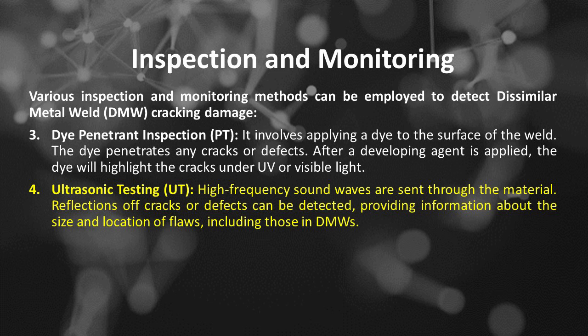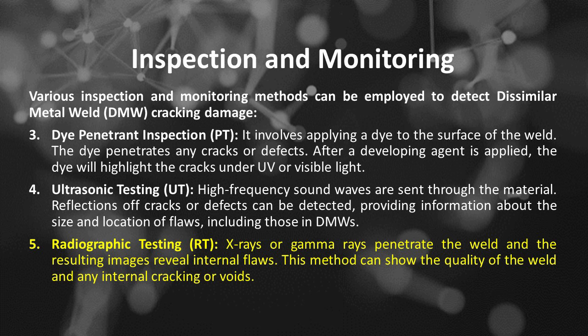Number 4 is ultrasonic testing, or UT. High-frequency sound waves are sent through the material. Reflections off cracks or defects can be detected, providing information about the size and location of flaws, including those in dissimilar metal welds.